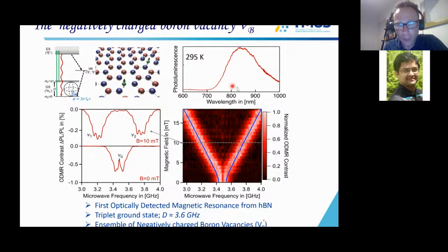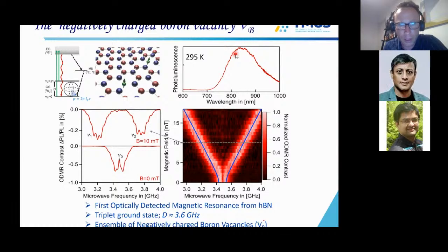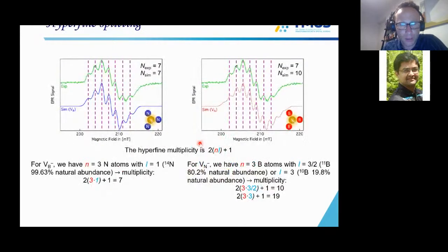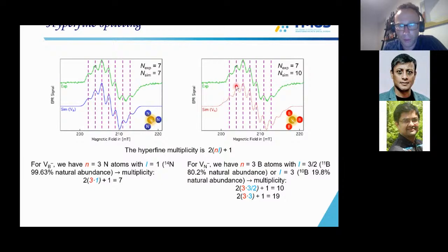So these are showing ODMR, optically detecting magnetic resonance. You can apply a magnetic field, or even at zero field, you can sweep your microwaves and see a very strong response here at about 3.4 gigahertz. And then you can apply a magnetic field, and this line will split as expected from a spin 1 system. And of course, having an ODMR, things become very, very easy. You can then use the hyperfine coupling, measure EPR, and resolve this hyperfine structure and really prove conclusively that this is a boron vacancy center.